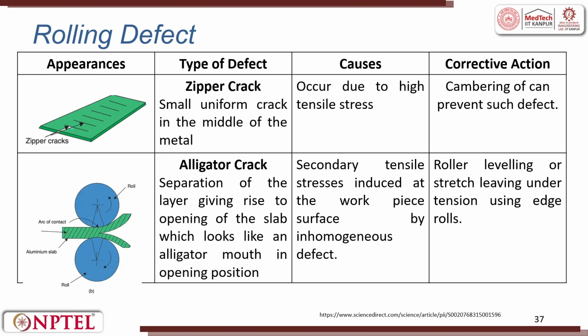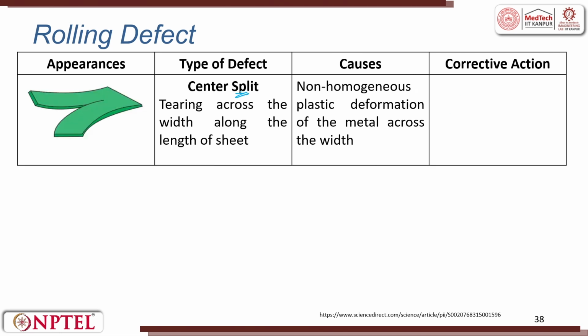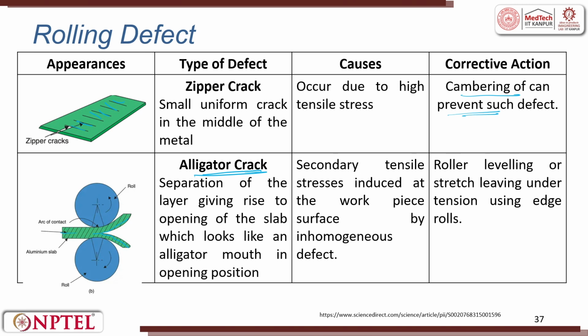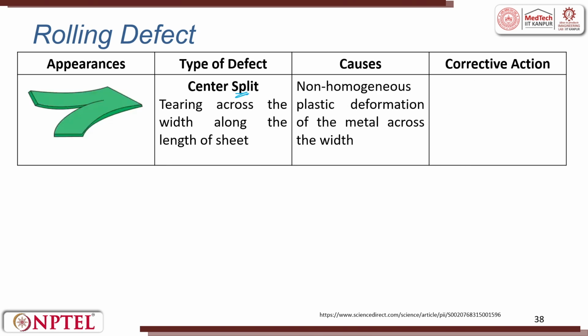You can also have zipper cracks, these are cracks which are seen all along the line, and you can also have something like an alligator crack. So, the contact is there and once it rolls and it comes out, it forms a crack like this. So, these are all improper stress strain application or the process parameters, the velocity, roll pressure, everything. If we start optimizing this, we can try to reduce it. The camber on the roll prevents the defects. So, this is alligator crack and this is center splitting which can happen.